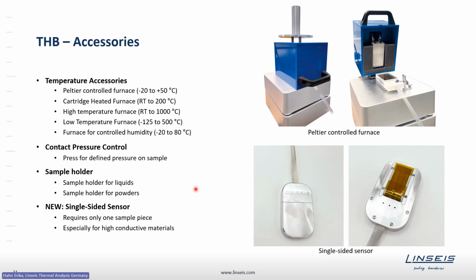For the THB, we also offer a lot of accessories to customize the instrument. A lot of different furnaces, for example, the Peltier controlled furnace going to sub-ambient temperatures and slightly elevated temperatures. We also have tools for contact pressure control, as well as different sample holders. And for the case that one cannot cut a large piece of material into two pieces, or doesn't want to destroy it, there is the single-sided sensor based on the QSS principle, where just one sample piece is needed to measure the thermal conductivity, especially useful for highly conductive materials.